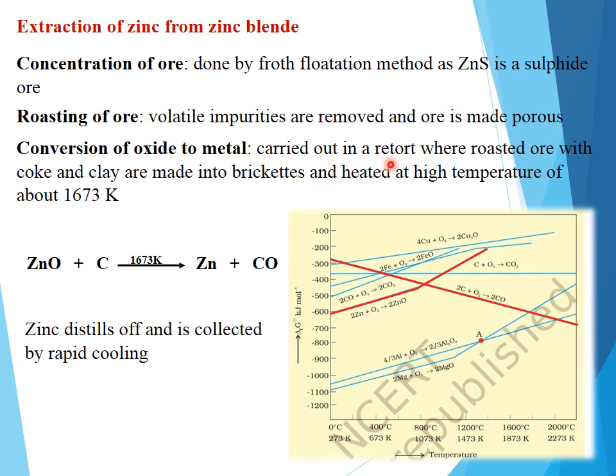In the conversion of oxide to metal, the zinc oxide will be taken in a retort, a type of furnace, where the roasted ore with coke and a small amount of clay, silica, which will be used as a flux to remove some basic gangue particles, is taken. These are all mixed and converted into briquettes, brick-like structures, and they are heated to a high temperature of around 1673 Kelvin. At this temperature, the zinc oxide combines with coke and forms zinc, and carbon monoxide is given out.